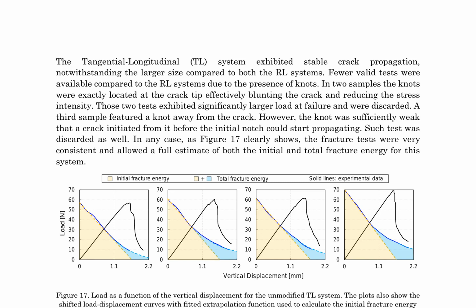Consistent fracture tests for the unmodified TL system are illustrated in Figure 17, showing the load as a function of vertical displacement. The plots also display the shifted load displacement curves with a fitted extrapolation function used to calculate the initial fracture energy, GF, and total fracture energy, GF.